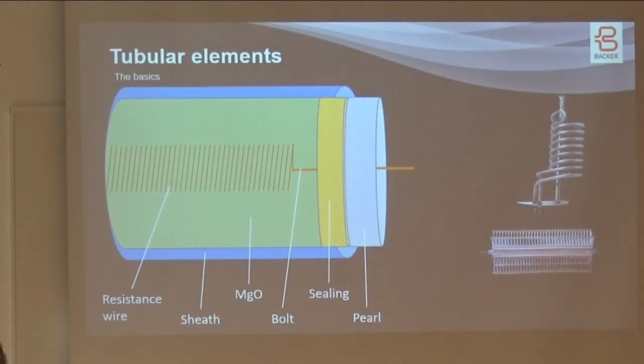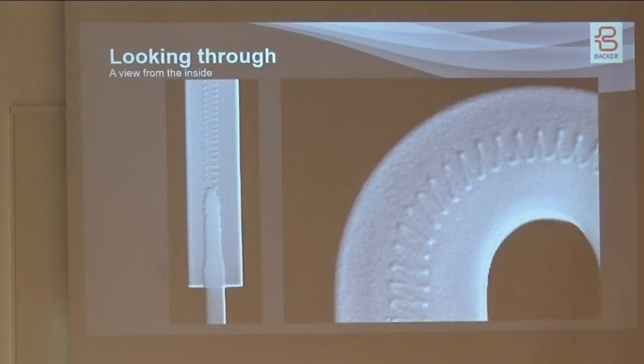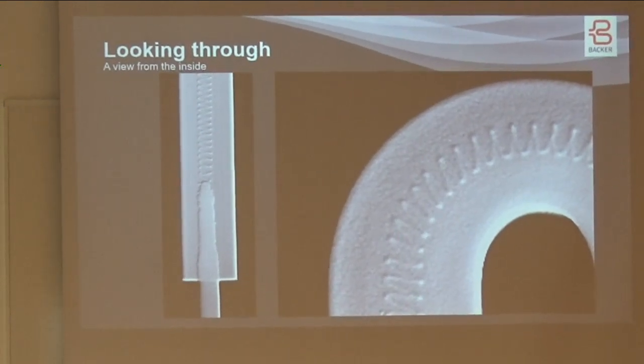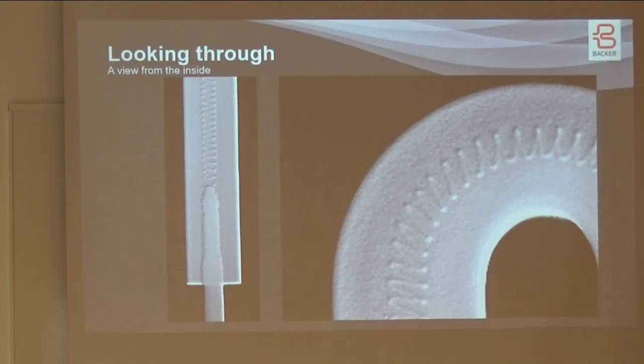And aluminum elements, stainless steel elements, and this is one of our big products as well. It is for water heating, for hot tub water in homes. If you look through, this is with ordinary X-ray, nothing more special, but still. So you will see the resistance wire, it's coiled, and while you fill it with magnesium oxide, you pull it apart a bit so that the coils are separated. And you see that even if you bend the elements, the magnesium oxide helps keep it nicely in the middle.